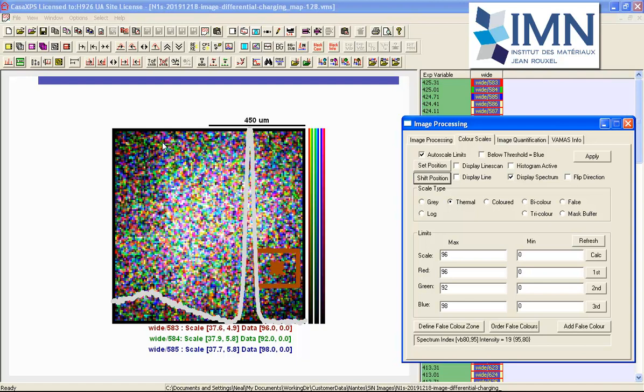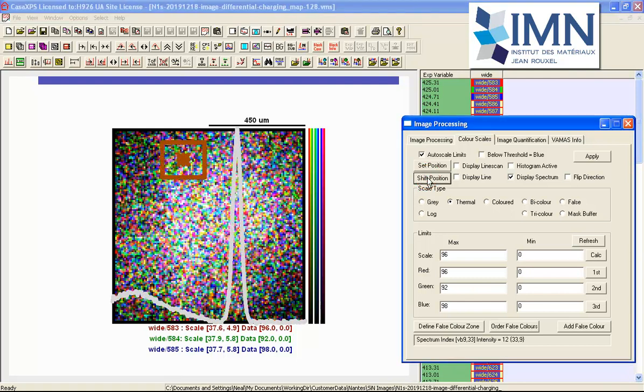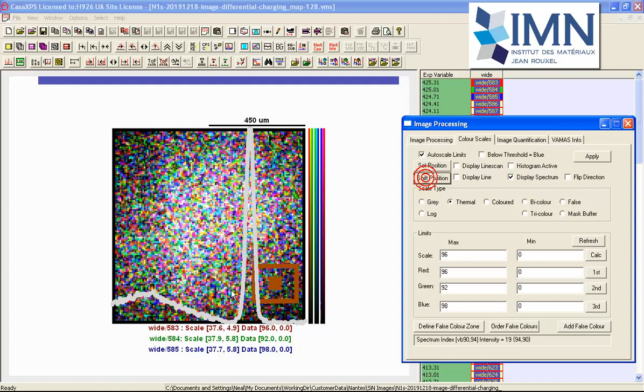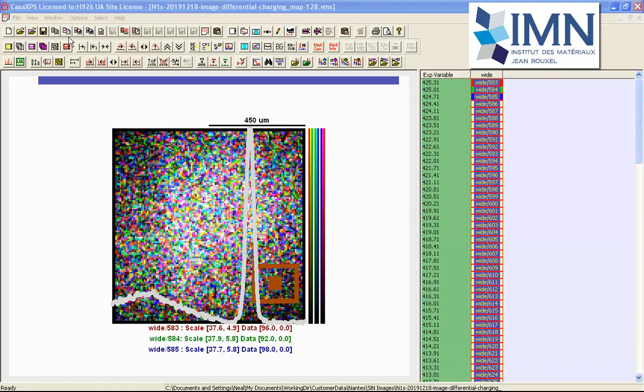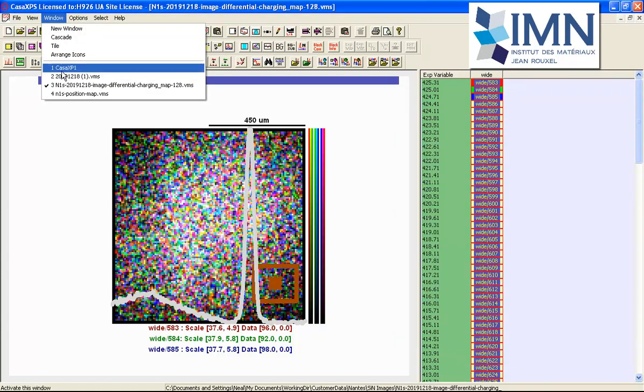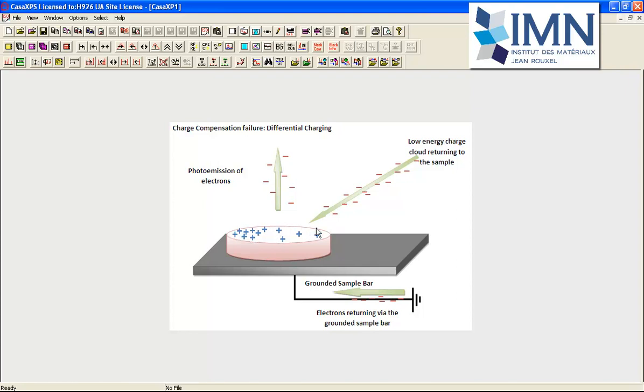This is indicating we have what looks like a single peak. If I choose a different position by clicking and then say shift position, a box of the same size creates a new spectrum and now we can see that there is a slight shift. Let me do this again. I am choosing a position in the top left-hand corner and say shift position. If we look at this peak when I press this button, you can see it shifts. So it does look like there is differential charging. The charge state at this point is different from the charge state at this point.